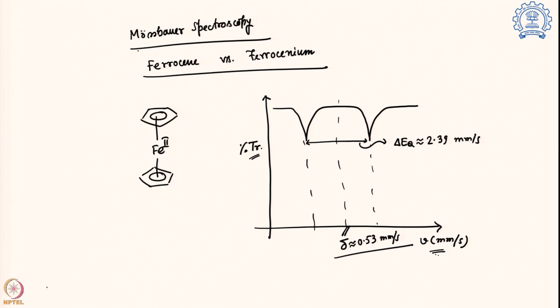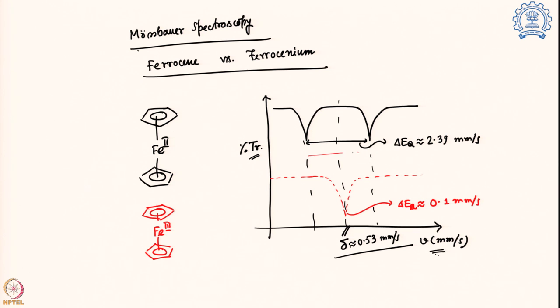Now, when we oxidize this system and go to iron 3 plus, how does it look? Very interestingly, we found that this almost becomes a singlet, where there is a negligible delta EQ value close to 0.1 millimeter per second. On this particular scale, where we are showing 2.4, it is almost negligible. But interestingly, the delta value remains almost the same.